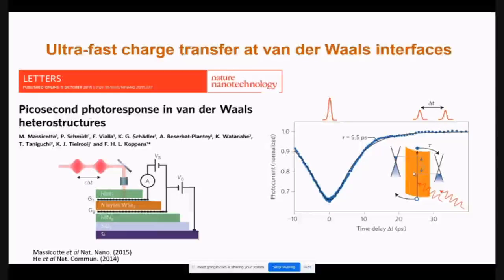For example, because the layers are so close, in spite of the van der Waals gap, which is about 0.3 or 0.4 nanometer, you can transfer electrons very, very quickly from one layer to the other. This is something which has been shown now. You can see the transfer can happen within 5 picoseconds or something of that sort. And this naturally raises possibilities of a new kind of detectors. I'm going to show you that, or many other